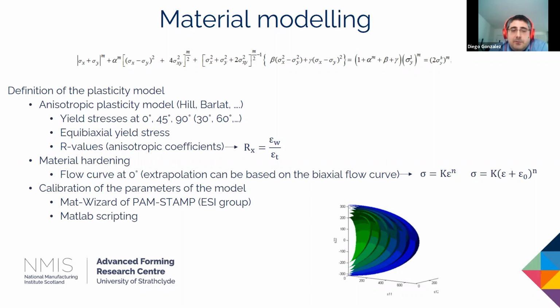For the material hardening, we will use the flow curves we obtain for 0 degrees, the direction of rolling, and we can extrapolate these flow curves based on the biaxial flow curve, and we can define the material hardening in an analytical manner using a simple power law, or a bit more complex power law, or in a tabular way. So we have different ways to precisely capture the material hardening and to introduce that in the simulation. And the last point to define this anisotropy is the calibration of the parameters.